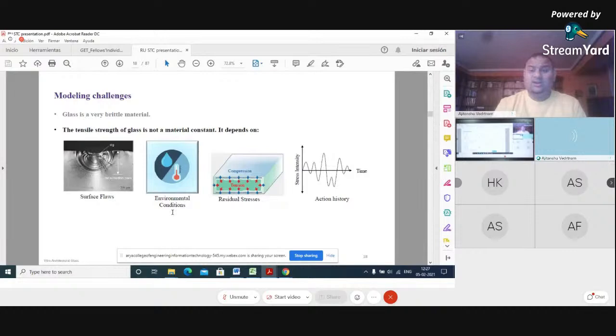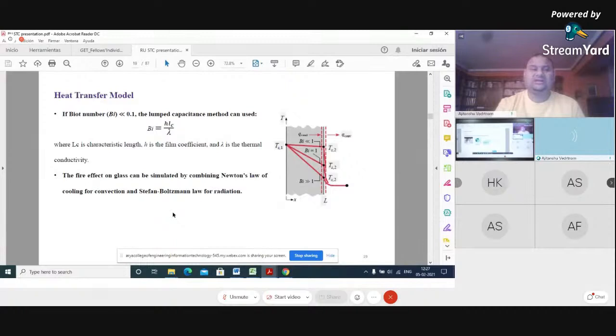it. For modeling, glass is a complex material because it has surface flaws, minor cracks which cannot be observed, residual stresses, environmental conditions, and non-uniformity, which cannot be modeled. It is very difficult to model this behavior, and we have tried to model it with the Biot number. And the Biot number, of course, you might be aware, gives the information about the flow of heat within the solid. If we want to predict the heat flow in a solid, we can do it by application of the Biot number.